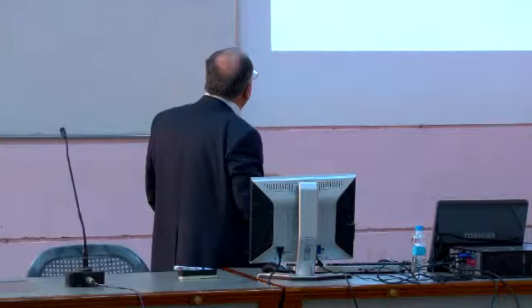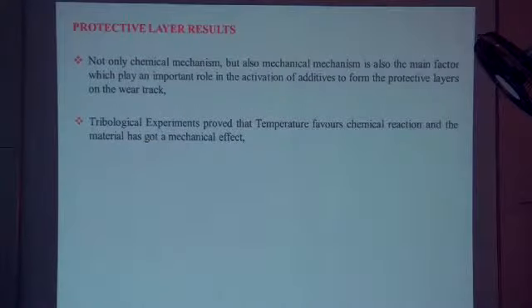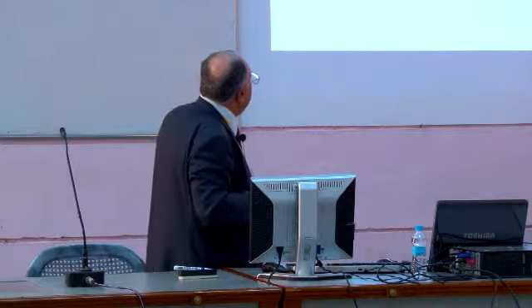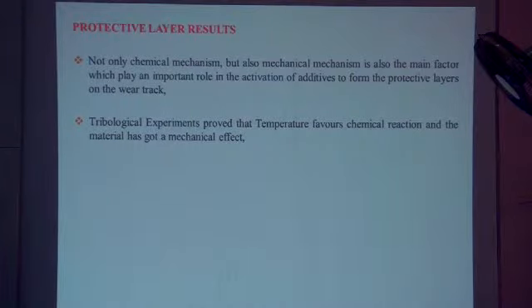The answer is this: not only chemical mechanism, but also mechanical mechanism is the main factor playing an important role in the activation of additives to form additive layers on the surface. Tribological experiments prove that temperature is very important. When you increase the temperature, the reaction gets faster, and the additives form better on the surface. So temperature is a chemical factor, and the material is eventually a mechanical factor affecting the formation of additive layers.